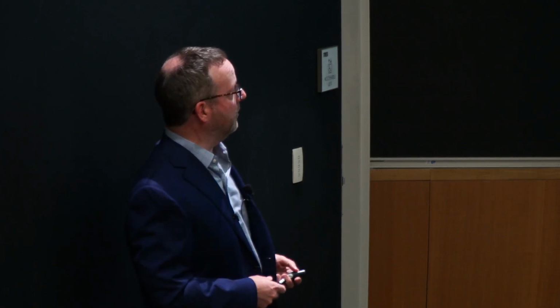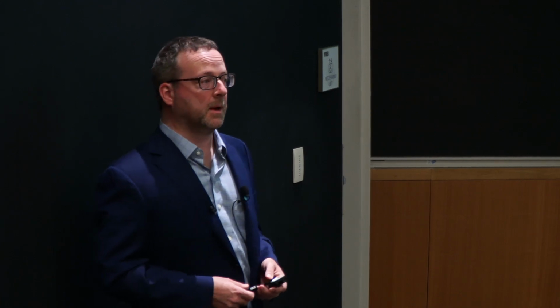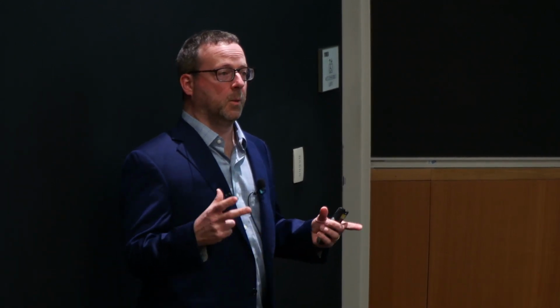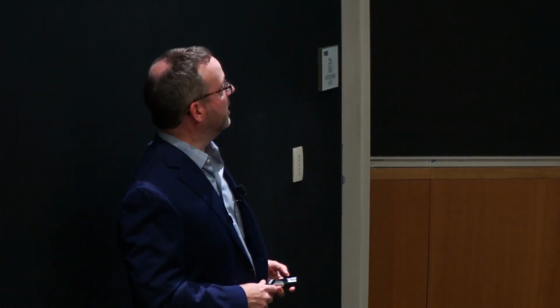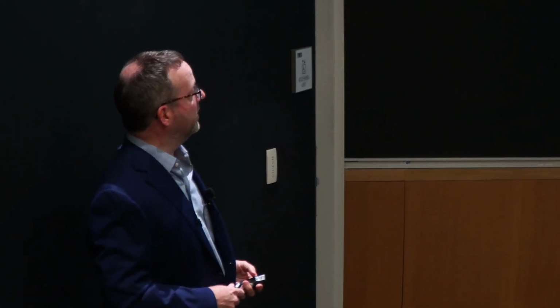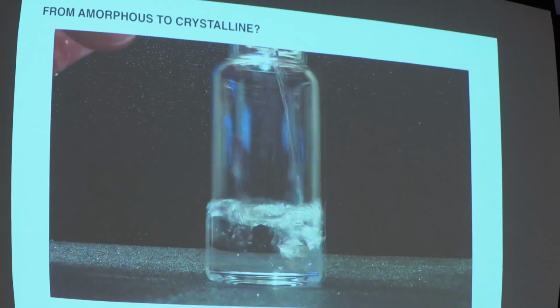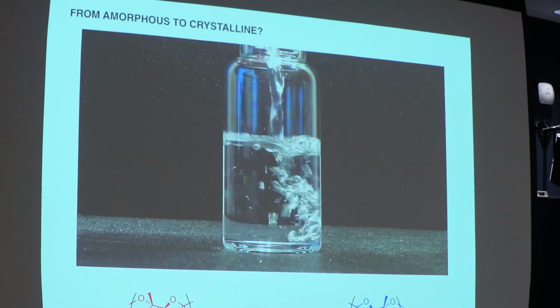So we thought, well, maybe if we mix them together, maybe it just mixes randomly and it's still amorphous, but maybe there's a chance that it makes what's called a stereocomplex, where the two enantiomers together can interact in a way that you can't do if you only have one enantiomer of the polymer present. And so I want to show you a simple experiment. You can dissolve these polymers up, and these are 1 weight percent in hexanes, so very dilute solutions. And we're simply going to mix the two together.